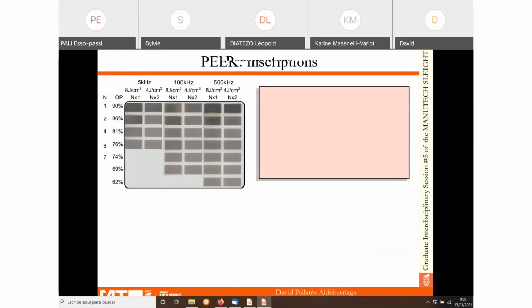And voila, finally, this is our first sample of results for PEEK. We have 3 different repetition rates. We have here 2 fluences, different overlap ratios. Okay. So now, what's the first thing that we can see here? Well, it's obvious that for higher fluence, higher repetition rate, and higher overlap ratio, the color is darker.